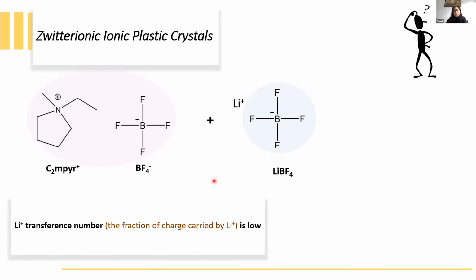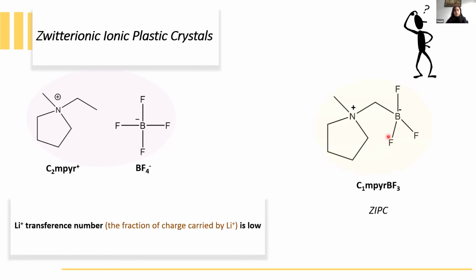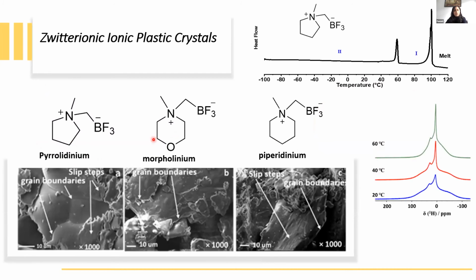We can even improve this number in plastic crystals if we can suppress the mobility of cations and anions in the plastic crystal. So one possible way is tethering the cations and anions by bonding them covalently together. In this case, we will have a molecule with net neutrality that won't move through the electrolyte. We call this brand new family of plastic crystals zwitterionic plastic crystals, which we expect will lead to a higher target ion transference number. So far, we reported 3 different zwitterionic plastic crystals based on a trifluoroborate anionic group and 3 different cationic groups, which are pyrrolidinium, morpholinium, and piperidinium.